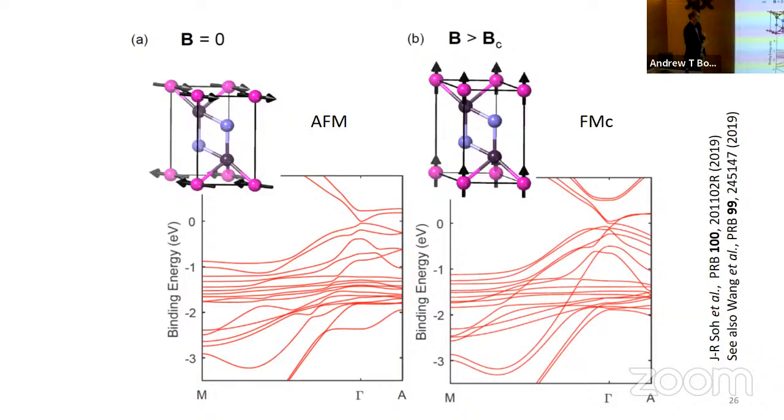However, because the threefold symmetry of the space group is broken by the ferromagnetic ordering in the layers, you actually get a gap forming at the place where the bands come together. So there's a very small gap here. It's only about 50 milli-electron volts, but nevertheless there's a gap here. And that means that in principle, if the system had a chemical potential right at this point here, it would be some kind of semiconductor.